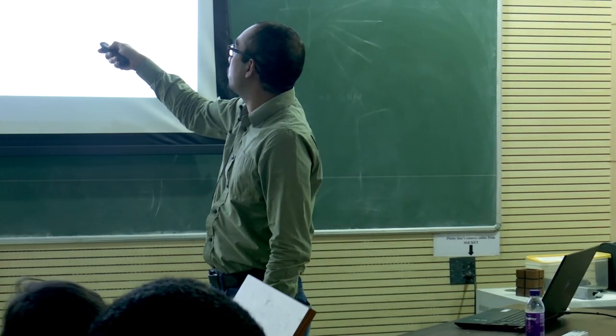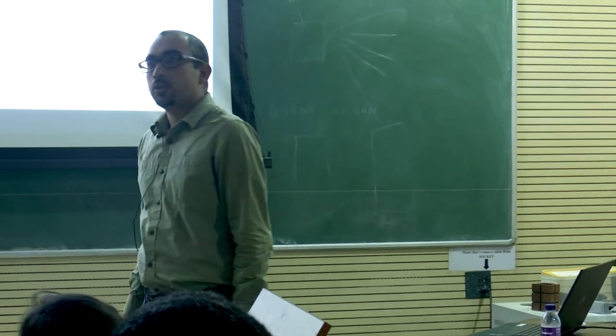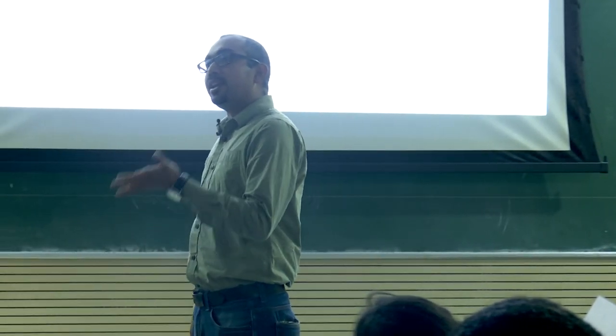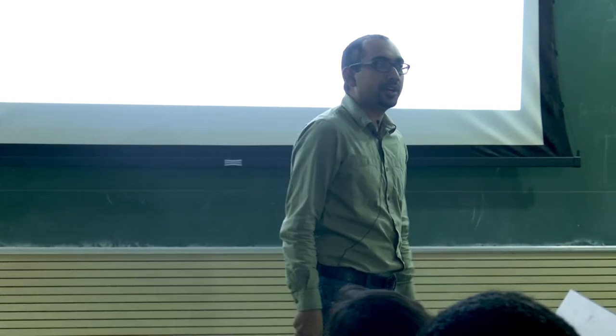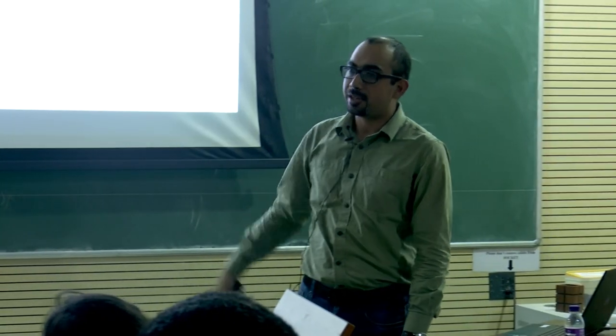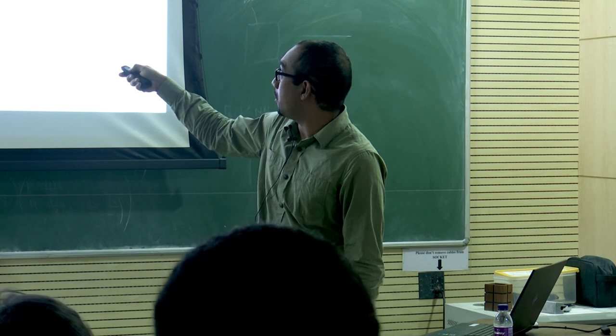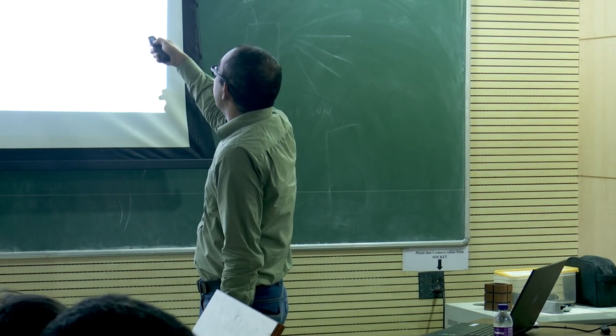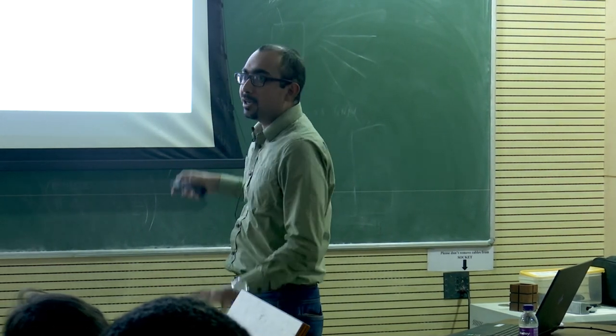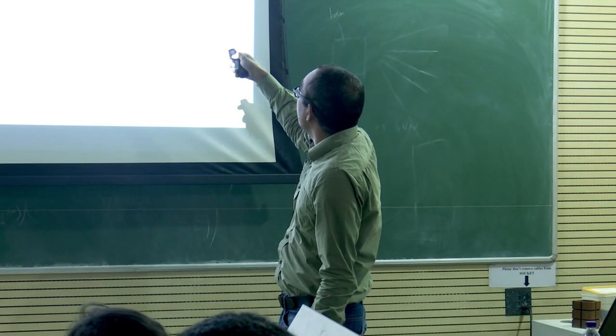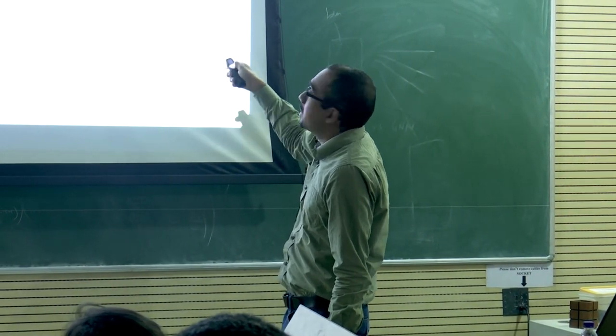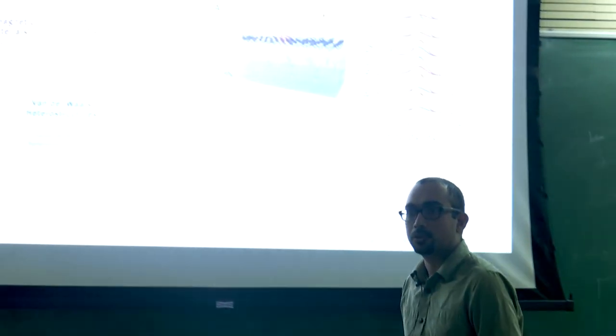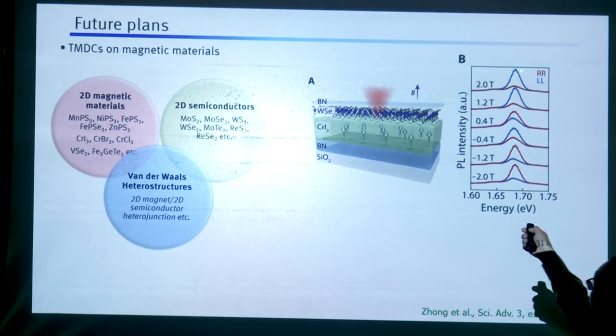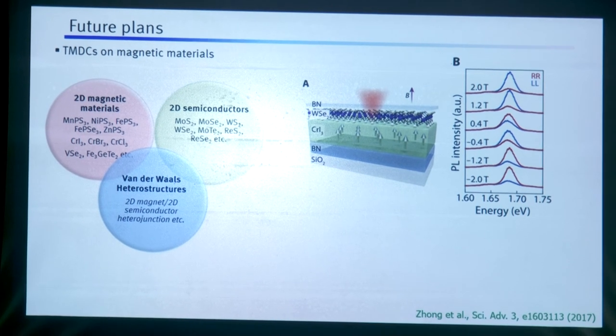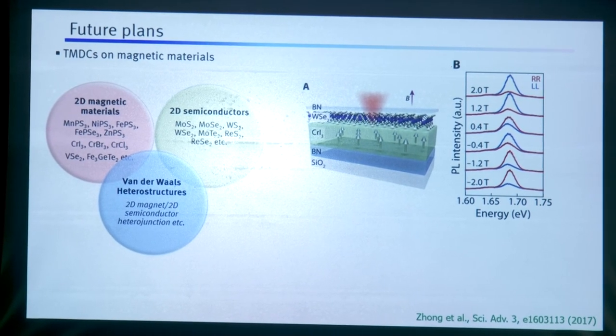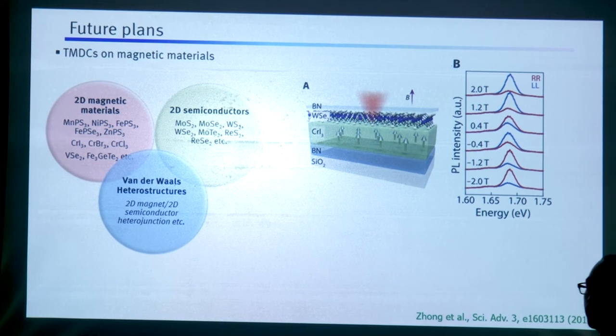So CrI3 is a 2D magnet and WSe2 is a 2D semiconductor. Now, the magnetic field is inherently present there. In fact, it's of the order of 15 Tesla, which is already present just due to the proximity of this layer. In fact, this polarization, which is shown here, I won't go into details. Now, we can tune this polarization with a small external magnetic field like 2 Tesla. So, this is possible now. Earlier, for such a polarization, you would probably need 30 Tesla. But now, you can tune this with 2 Tesla. So, you can tune the population with 2 Tesla.